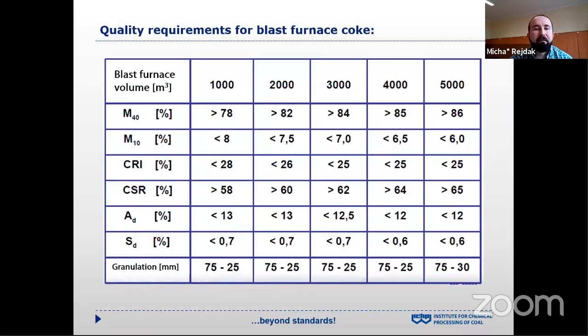Of course, for different blast furnaces, there are different requirements for blast furnace coke. As we can see, the higher the volume of the working chamber of the blast furnace, the better quality the coke should be. We can see the CRI should be lower, CSR should be higher. As I mentioned before, when we have higher working volume of blast furnace, there is higher mass of the iron bearing and in general the feed to the blast furnace.